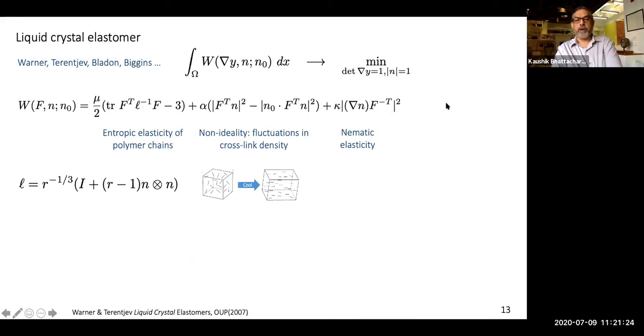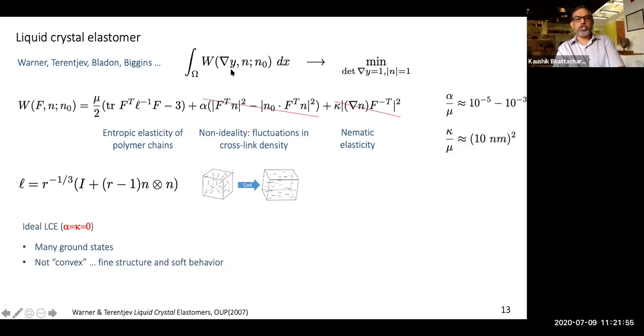And the third, finally, you have the liquid crystalline elasticity, the Frank elasticity, and that's basically the spatial gradient of n squared in a certain approximation. And this is the energy that you're trying to minimize under the constraints of incompressibility and the fact that your director is a unit vector. So it turns out that these two numbers are small. So the early part of the theory was done with what was called ideal materials, where alpha and kappa were neglected. And what I'll show you is that in this case, even this energy is actually extremely non-convex. So let's look at that.